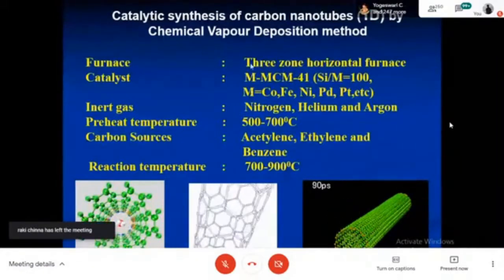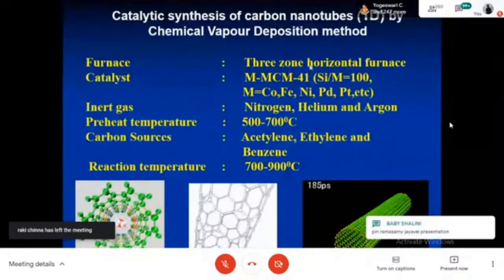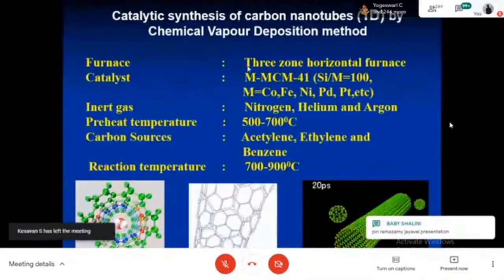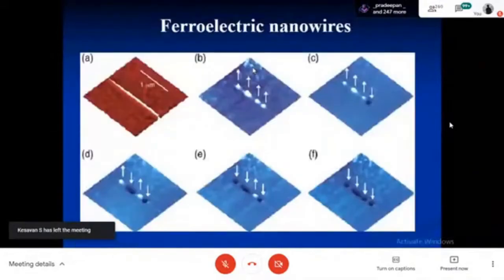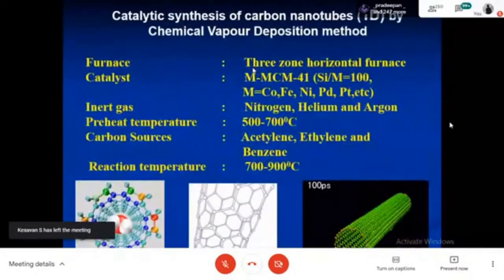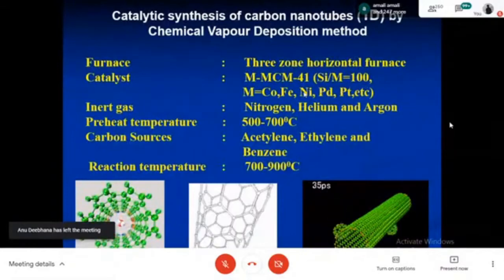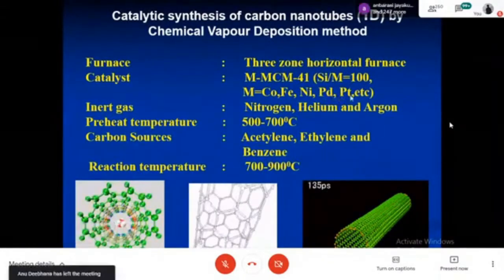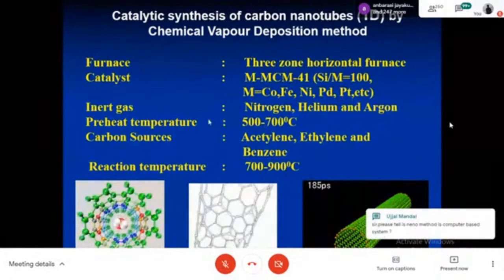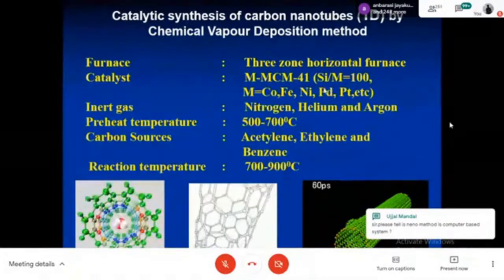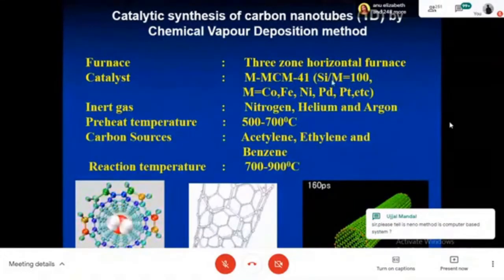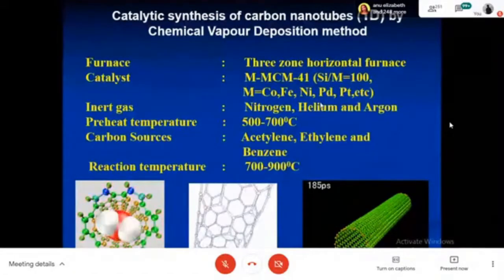And conveniently, we can have a conventional 3-zone horizontal furnace. And for very specific requirements, we have to go for a 5-zone furnace also. And we can use any of the metallic catalysts like cobalt, iron, nickel, palladium, platinum to enhance the reaction in the CVD process. And there are some templated materials that can also be used for them.